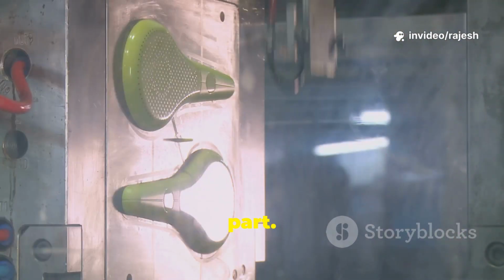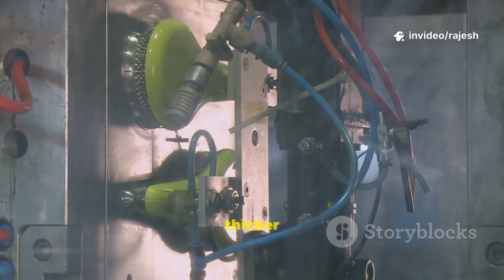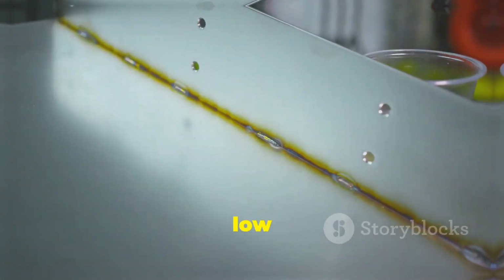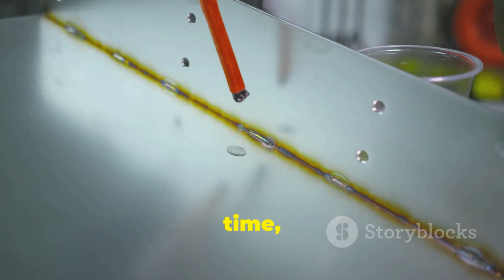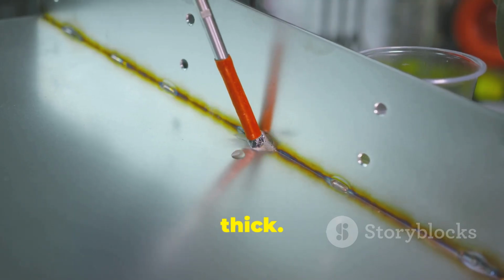Number 4, sink marks. These are little dents or depressions, usually near thick spots on the part. Sink marks happen because thicker areas shrink more during cooling. The usual suspects: low packing pressure, not enough cooling time, or just having walls that are too thick.